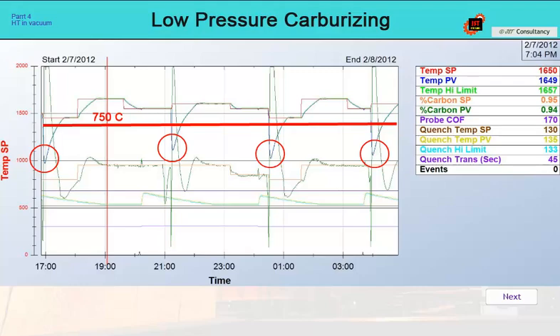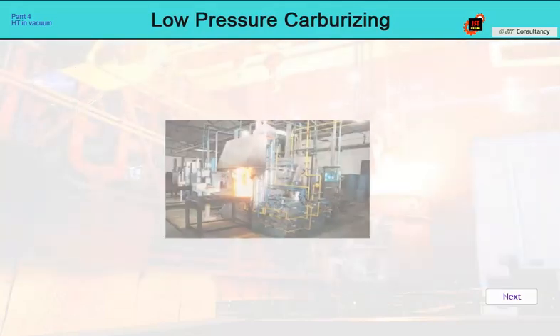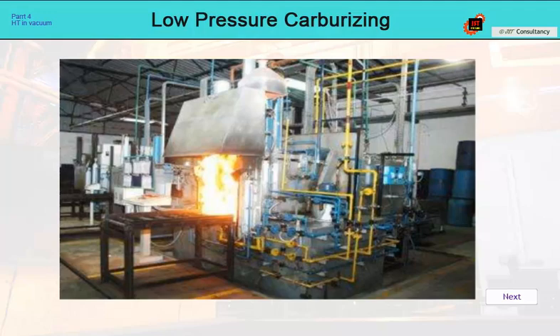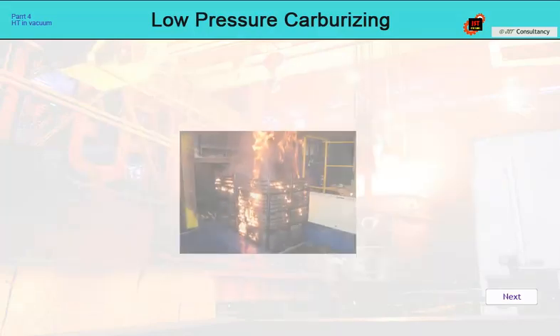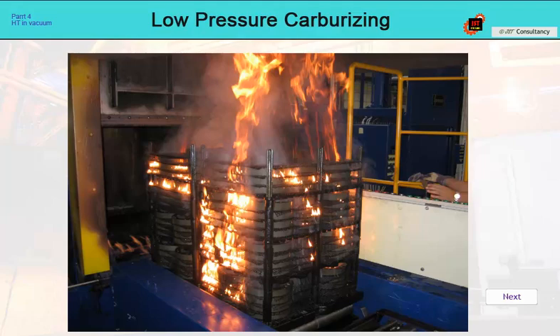Even if the furnace is tight, and all combustion processes take place inside without the presence of oxygen, in the case of loading and unloading, the door must be opened and the tightness of the furnace must be ensured by flame curtains. This can be critical, especially when quenching small parts in oil, where there is an unfavorable ratio between the surface area of the batch and the amount of oil on the parts.